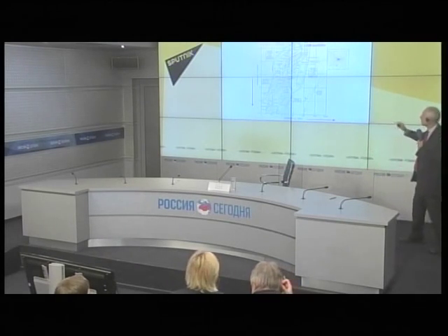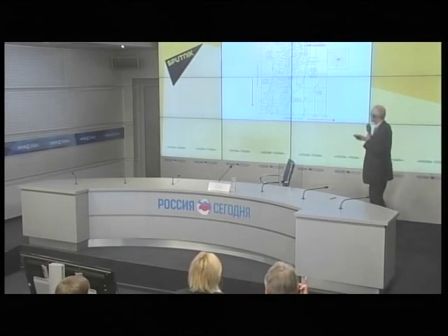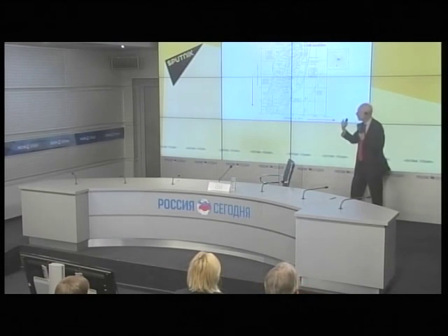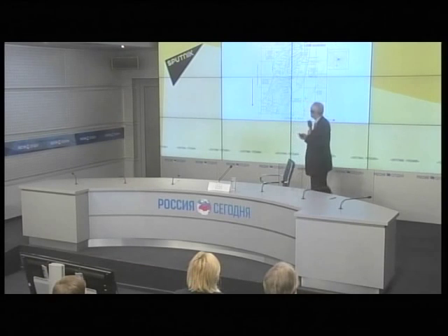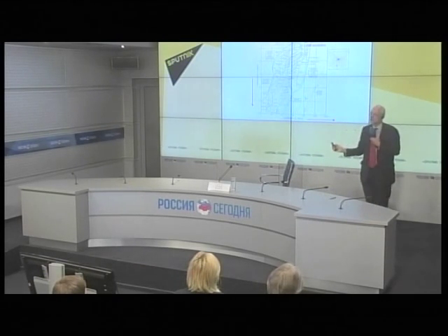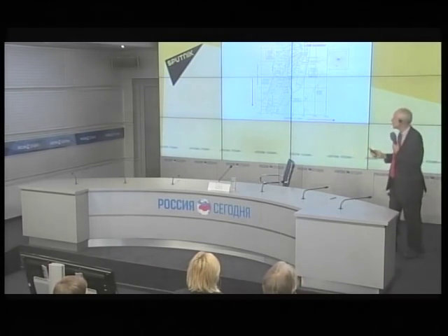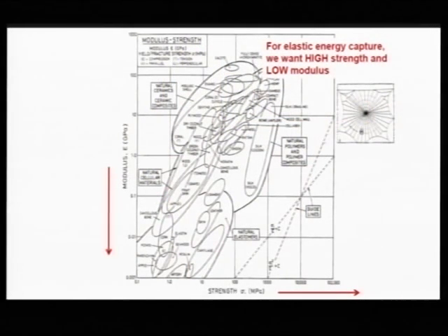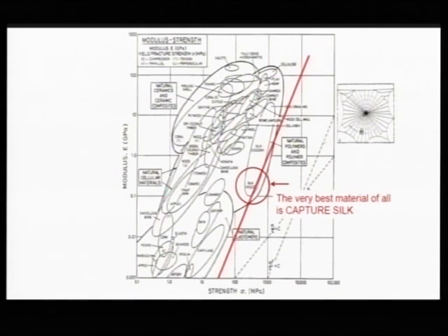So, of course, we need to look at one of these charts. We know what we want to store energy. We want a high strength. And we now know that we want a low modulus. So we want, on this chart, to be as far as possible towards the bottom right. Well, here's a map of all the materials that nature has available. Here's the relevant line of the gradient we have. And by now, you will, of course, not be surprised to find that of all the available materials, nature has chosen the best one. This is, in fact, the silk from a spider's web capture line, which has the best combination of properties of any of the natural materials. It's significantly better than anything else.